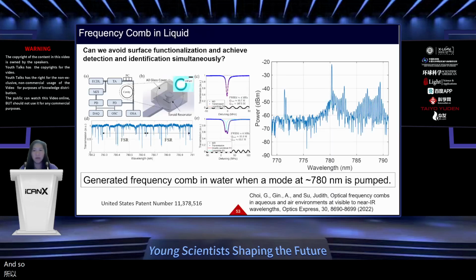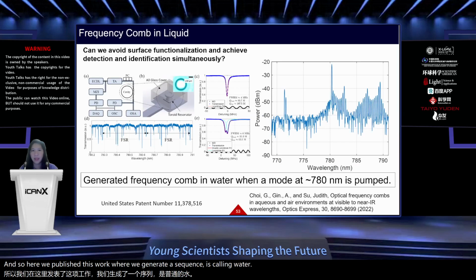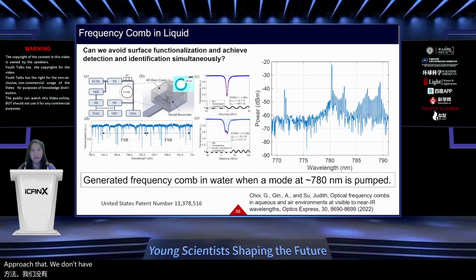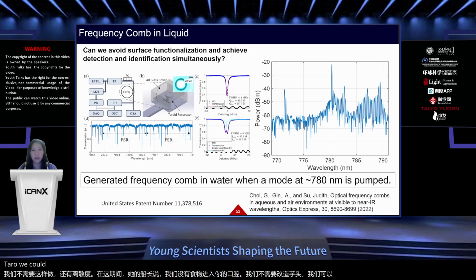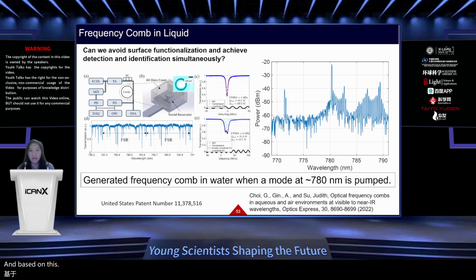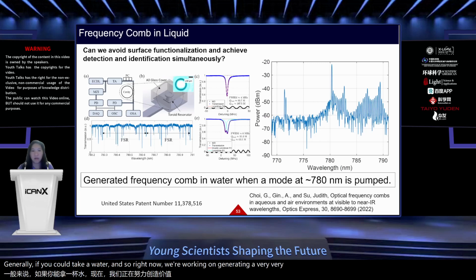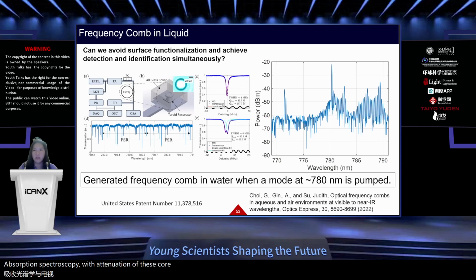And so here we've published this work where we've generated a frequency comb in water at this near infrared wavelength. We use what's called an avoided mode crossing approach, so that we don't have to do dispersion engineering of our cavity. We don't have to engineer the cavity, we don't have to engineer the material. We can just use our toroidal biosensor, which we've already shown is capable of very high sensitivity biosensing. And based on this, we can generate a frequency comb in water. Right now we're working on generating a very broadband comb in water, such that we can do simultaneous absorption spectroscopy, looking at the attenuation of these comb lines, as well as detection, looking at the shifting of these.